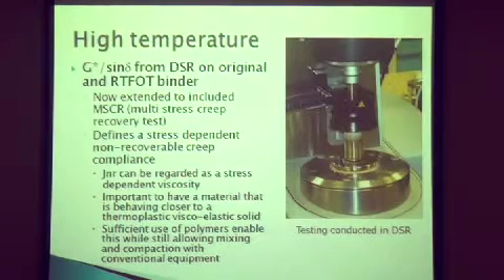JNR really is a stress-dependent viscosity. You know, sometimes in engineering we put these complicated words there, non-recoverable creep compliance. It sounds like a complicated word, but really it's just a viscosity, okay? What we're doing here is we're capturing something which is viscosity. It's trying to get something that's behaving closer to a viscoelastic solid material compared to a viscoelastic liquid. All binders that you get from an asphalt refinery, bitumen, just regular bitumen, whether it's blown, whether it's oxidized, whether it's a pitch bitumen, they will be a viscoelastic liquid.